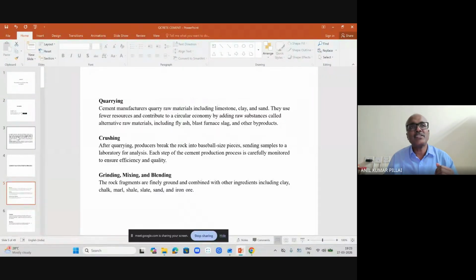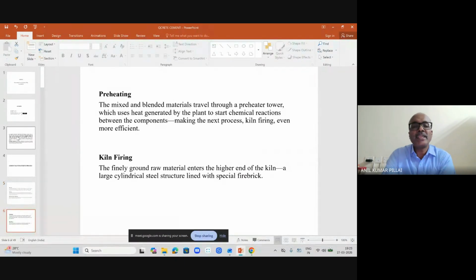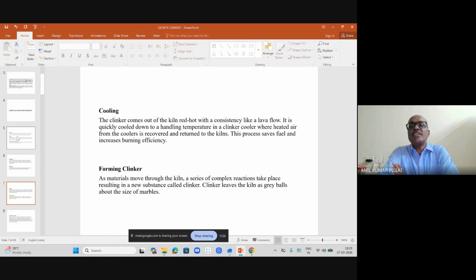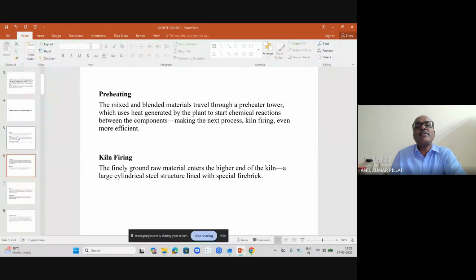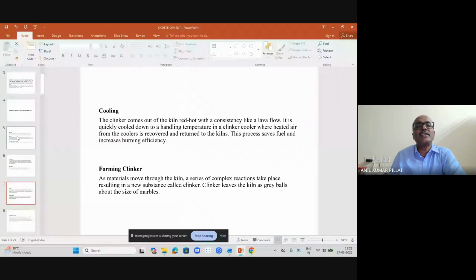You can manufacture a cement of very high compressive strength, but can you maintain it over a period of time? That is very important. And that is what you will find in the various steps, starting from quarrying to crushing, grinding, mixing, blending, and then you preheat, and then you fire the kiln. And then the cooling takes place. Both the kiln firing at a very high temperature of 1500 degrees centigrade, and the cooling to 100 degrees centigrade, need a lot of monitoring.